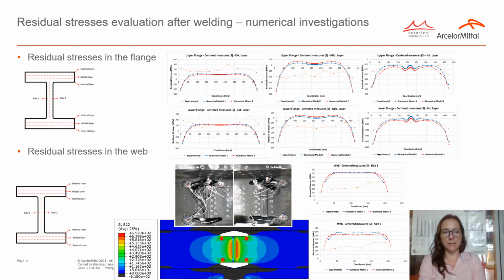In this slide, I present the comparison of the residual stresses. In the flanges, it can be observed that the residual stress values obtained using the numerical model are overall aligned with the experimental outputs, with a concentration of stresses in the beam flange extremity where the appendices are welded to the beam. The biggest discrepancy between the numerical and experimental directional stresses is located in the middle layer of the flanges, which is explained by the fact that this is a region of stress transition between compression and tension.